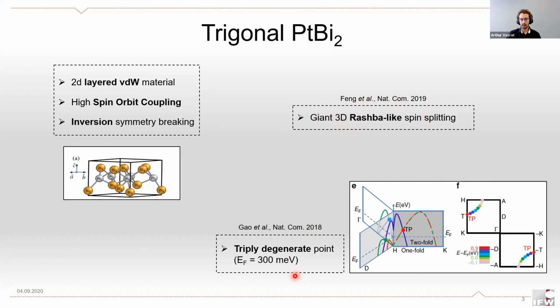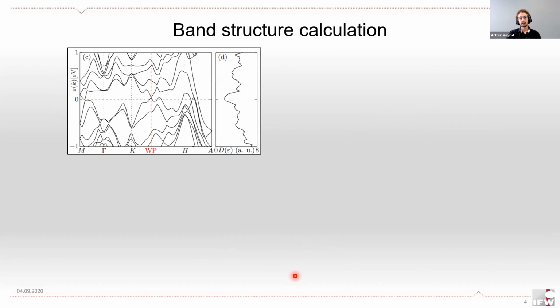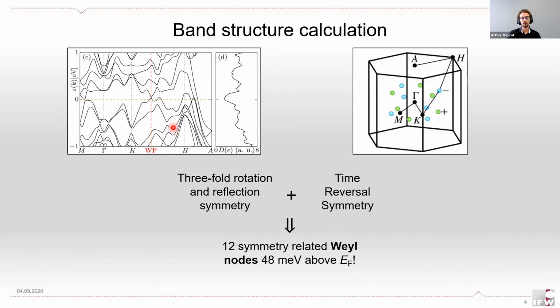So this is quite high for us to be able to observe using transport measurements. But nonetheless, this should show you that trigonal platinum bismuth 2 is an interesting material from a topological point of view. And indeed, when we made some band structure calculations in our institute using density functional theory, we found the existence of 12 symmetry-related Weyl nodes here at about 48 meV above Fermi energy. As you can see here, though, the density of states does not vanish at the level of the Weyl nodes, and that is due to the presence of a number of other bands crossing the Fermi energy.